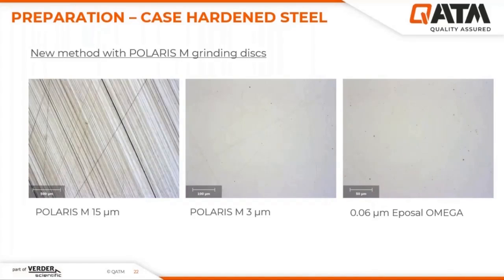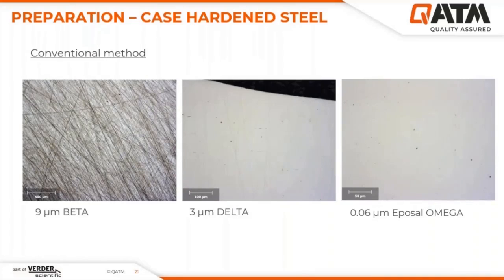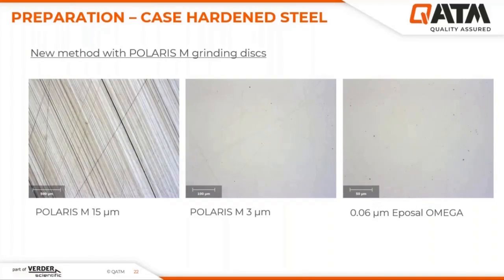In comparison, you can see the micrograph on the left here after grinding on Polaris M with 15 microns. Of course, you will see a significantly coarser pattern as 15 micron abrasives are used instead of 9 microns, and also we have bonded abrasive grains here, which also affects the grinding pattern. In the middle, we have the 3 micron step again, this time with the Polaris disc. And if you compare with the 3 micron diamond polishing in the previous slide, you can see that there is no really significant difference here.